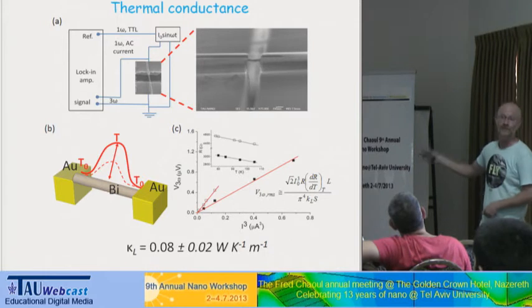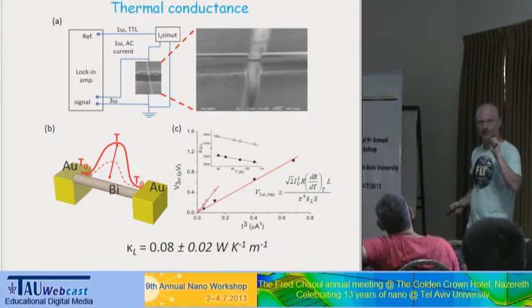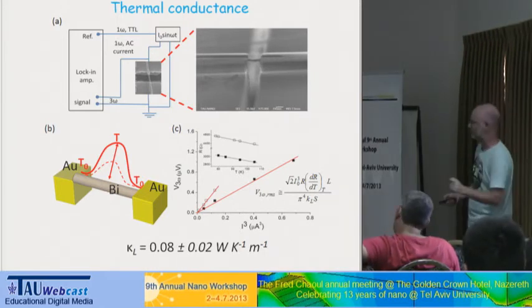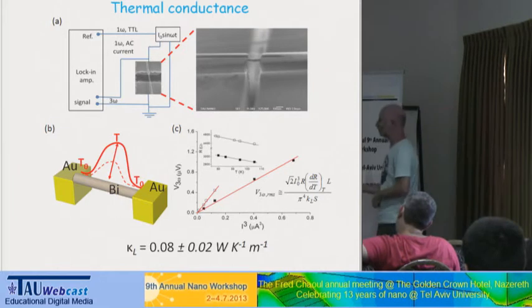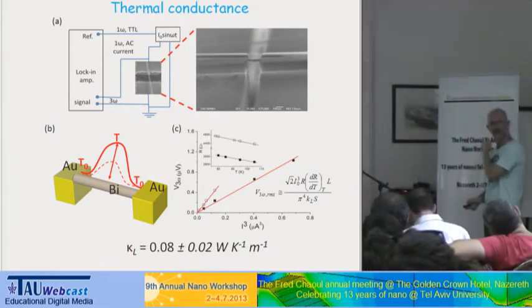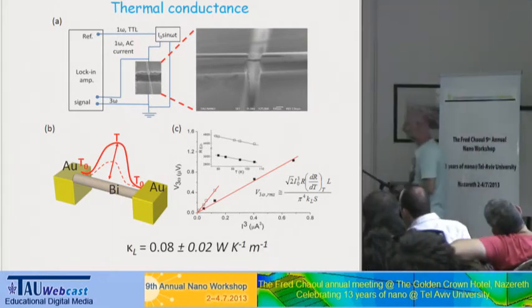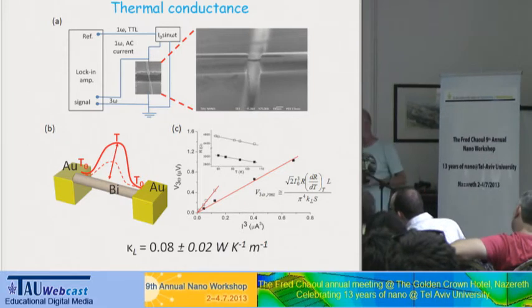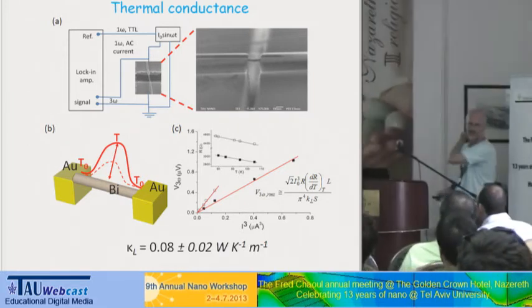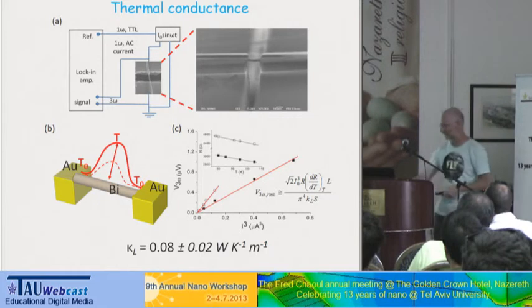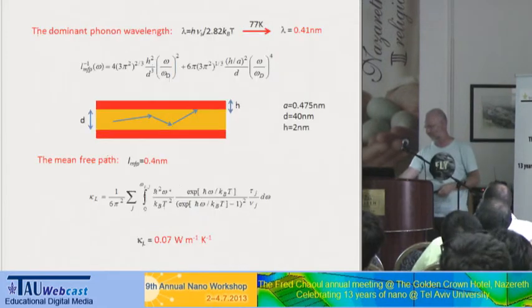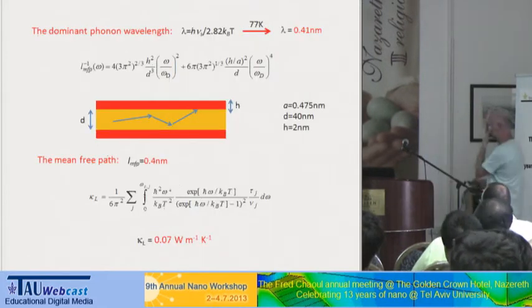This is in the amorphous solid. We have a single crystal structure that behaves like an amorphous material. This is very surprising, extremely surprising. But then we had to find out why this is so, and we checked this a zillion times to make sure that we are not making any errors here. And we developed the following model.